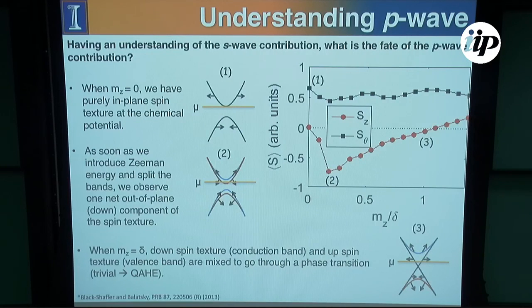imbalance between the px plus py and the px minus py. You actually still have some non-zero projection of the S-wave component within the plane of the topological insulator that still gives you some helical pairing. And as soon as you still have some helical pairing, you're always going to have some S-wave contribution here, which was kind of a bummer.